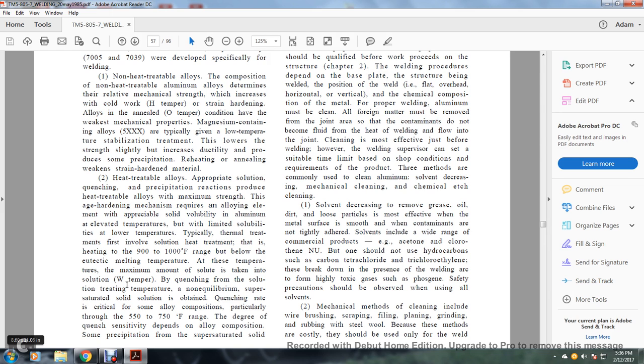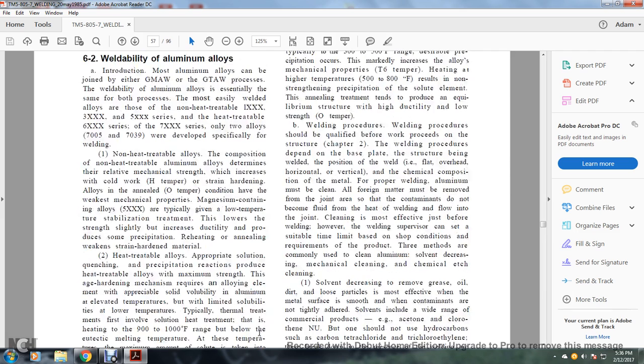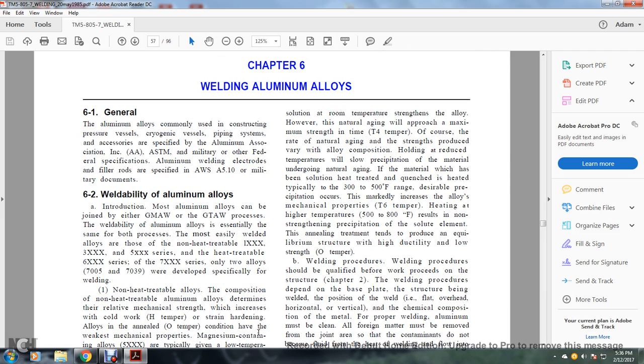At this temperature, the maximum amount of soluble solute is taken into solution. This is the W temper. Quenching from the solution treating temperature produces a nonequilibrium, supersaturated solid solution. The quenching rate is critical for some alloy compositions, particularly through the 550 to 750 Fahrenheit range. The degree of quenching sensitivity depends on the alloy composition. Some precipitation from the supersaturated solid solution occurs at room temperature, strengthening the alloy. However, natural aging approaches the maximum strength of the T4 temper, and the rate of natural aging and the strength produced vary with alloy composition. Holding at a reduced temperature slows precipitation in material undergoing natural aging.